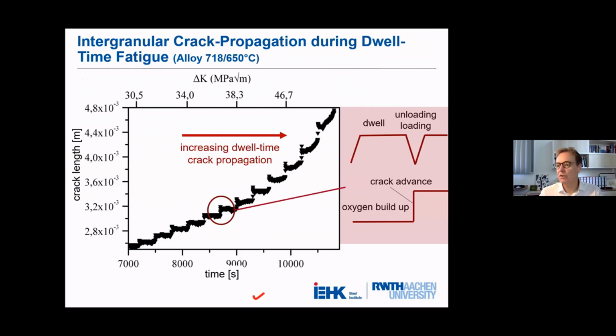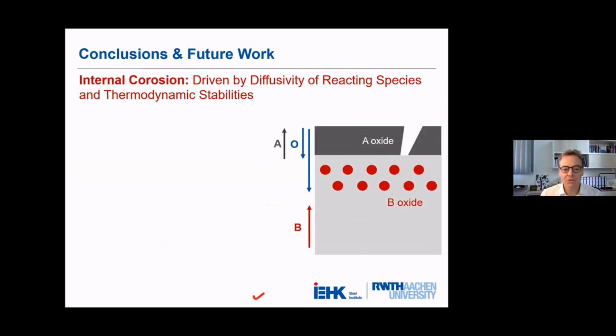And if we have a closer look at what's going on, then during the dwell time we have oxygen buildup, and during the load reversal we observe the crack advance. So once we know about this mechanism, we can look deep inside and adjust the grain boundary structure. For instance, we can apply grain boundary engineering type processing in order to improve the resistance of the material to this kind of damage. But since my 30 minutes are over, I would like to come to some conclusions.